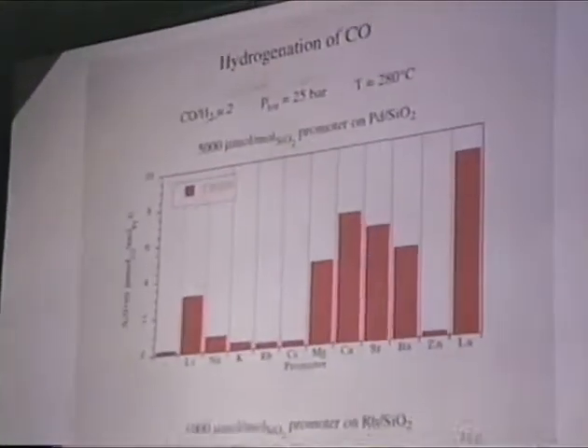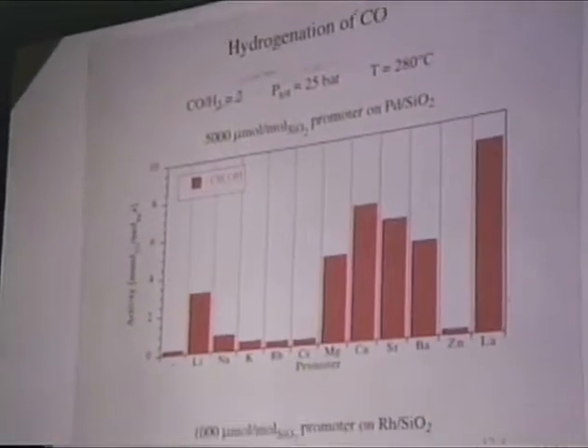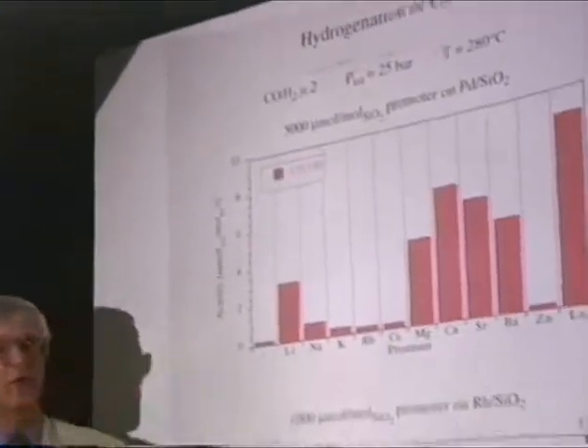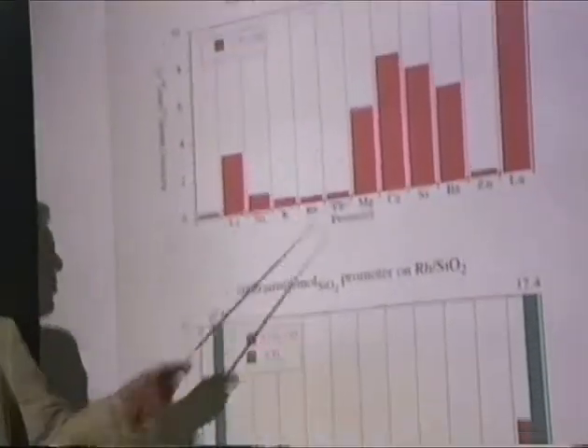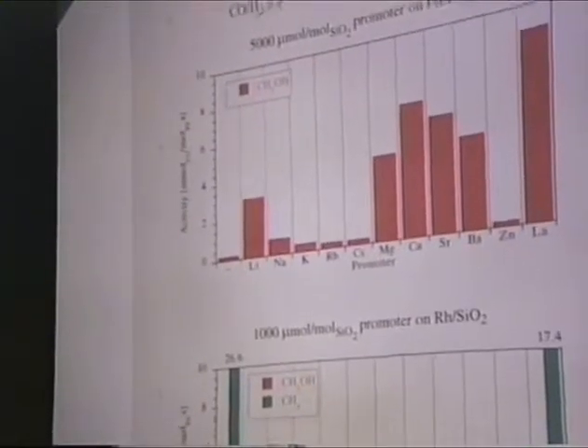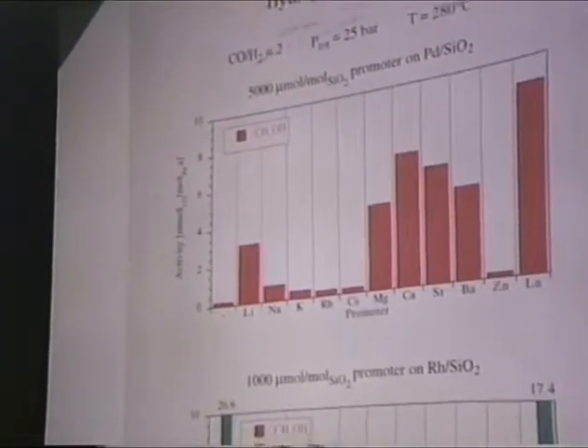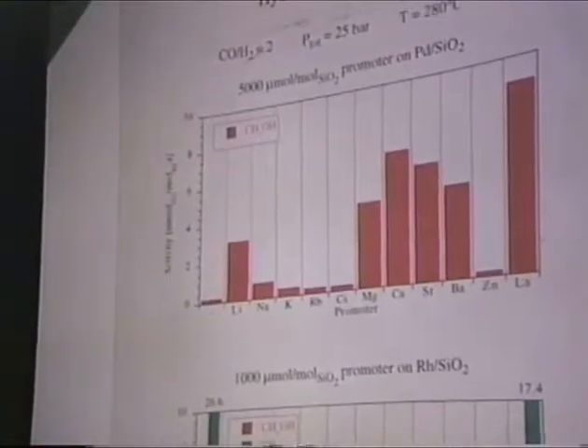You are right. It's very difficult to address that question. We should do a lot more work to really answer questions like that, and that's why we must do more fundamental work, let's say, with foils and single crystals and like that. The problem is that there are at least two effects. One is, let's say, an electronic effect going from lithium to cesium or magnesium to barium, right? And then you ask yourself your question, why is it going down here? Why is there a maximum there? However, this is, let's say, convoluted with the other problem, that is diffusion over the surface.